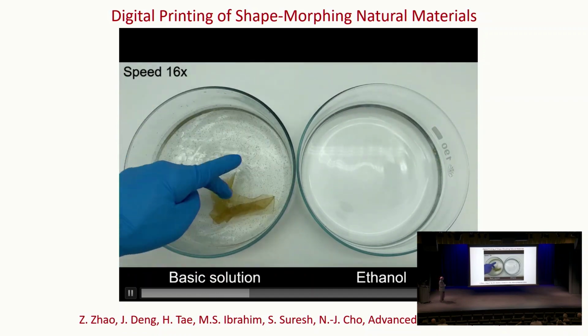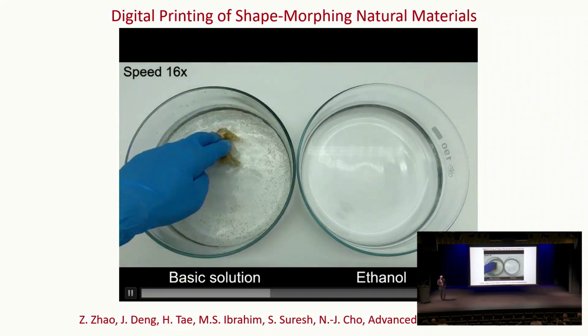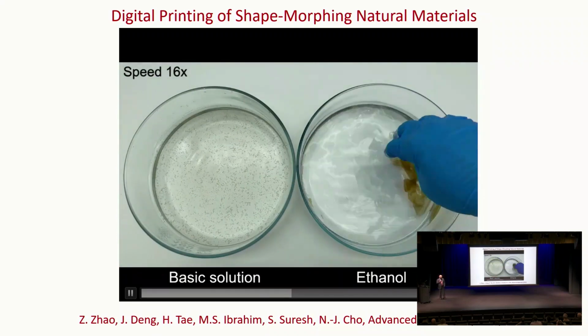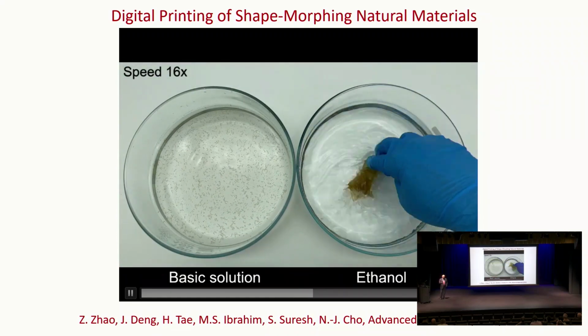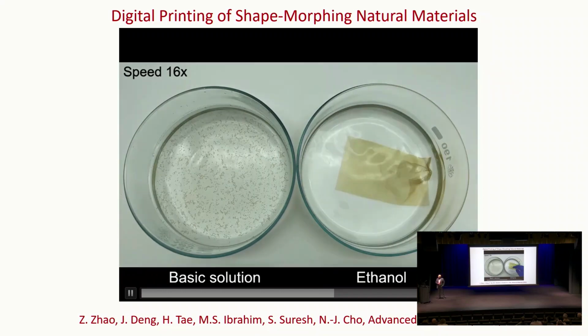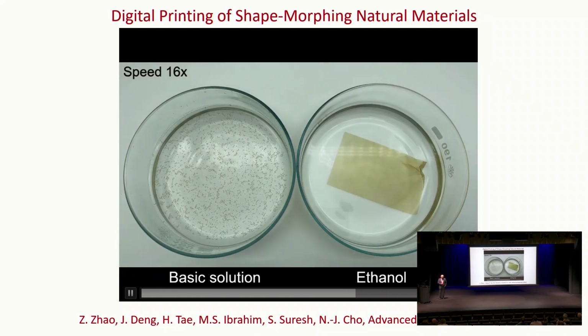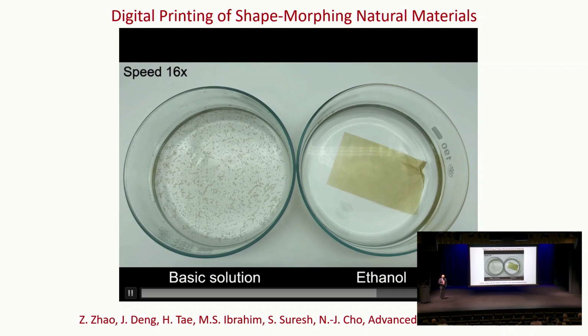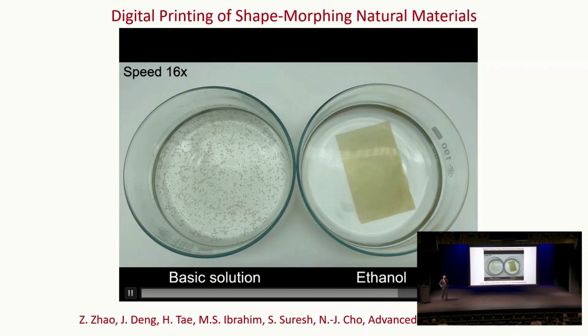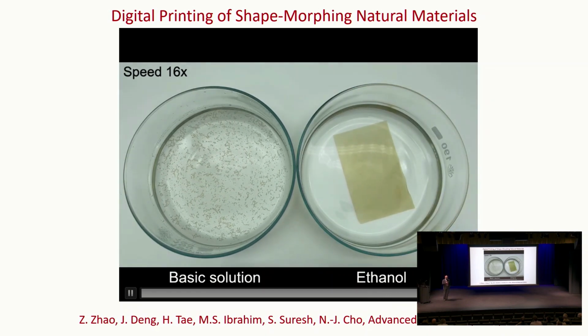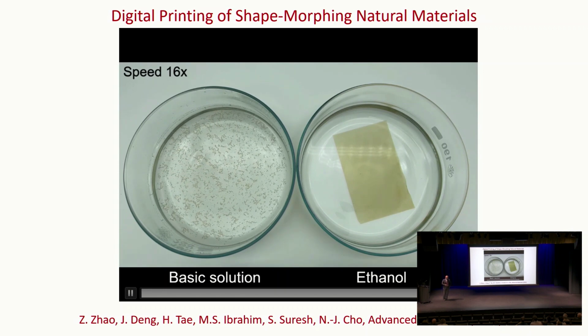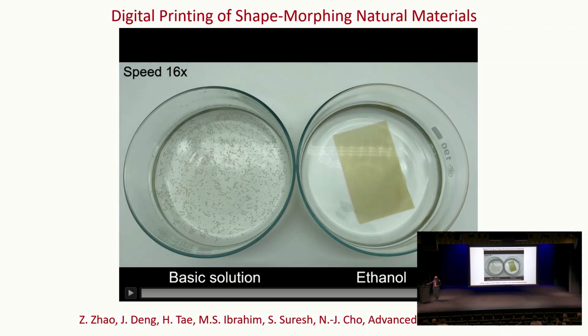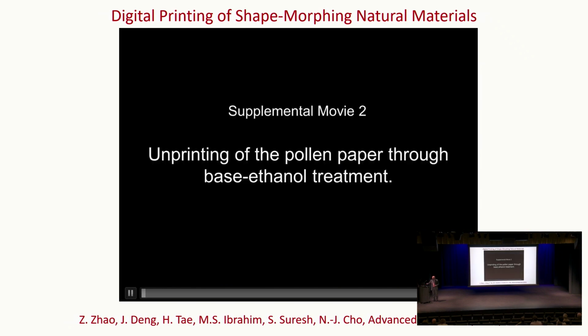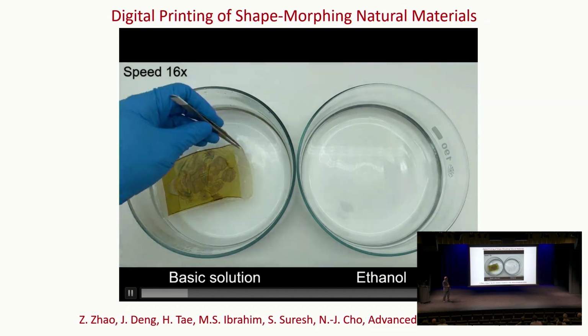We use a solution. We completely take everything out. This is printed using a regular printer, regular inkjet printer. Then you put it in ethanol. You get your paper back. Now you use the same paper to dry it, you reprint it. Keep doing it over and over again. So we did that 9 times. The student who was very good, who was working on this, decided 9 times was enough. It was getting to be boring.